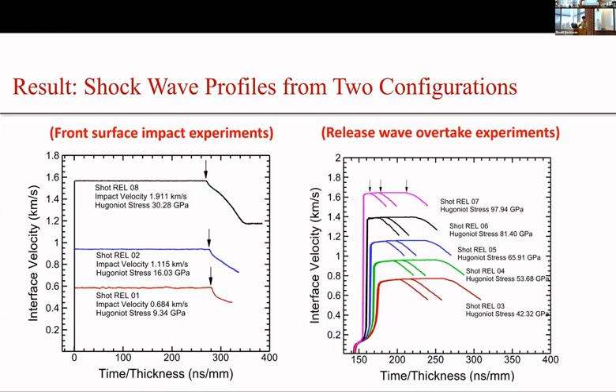The measured wave profiles are shown in these two figures, where we have conducted 3 low stress experiments using the front surface impact and 5 high stress experiments using the release wave overtake. The black arrows on the curves represent the arrival of the release wave, which travels at the longitudinal sound speed. Using that information, we can get the sound speed in the shock compressed tungsten carbide sample.